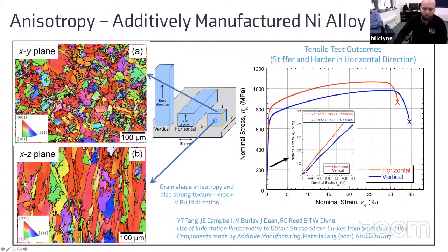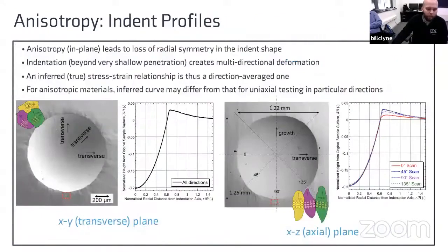So what happens when we indent this material? Well, on the left-hand side, we can see an SEM micrograph of the indent after indenting in the XY plane. In this case, the indent is radially symmetric. So in all directions, all of them being transverse directions, we produce the same scan. So there is no difference depending on which orientation we take our profilometry measurements.